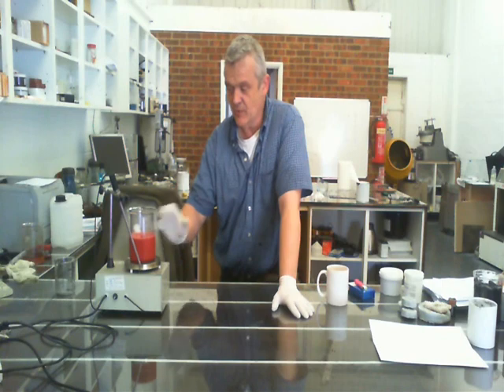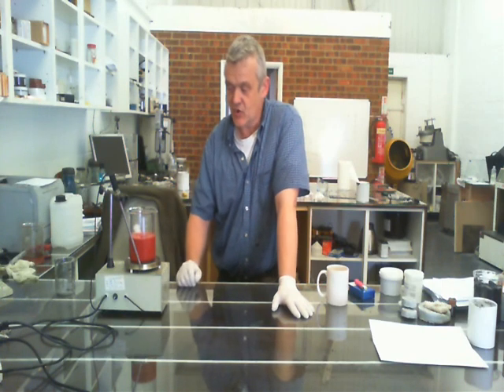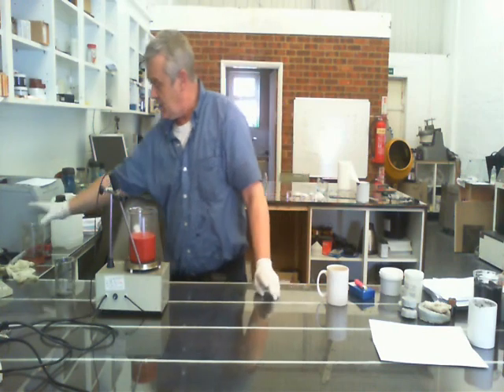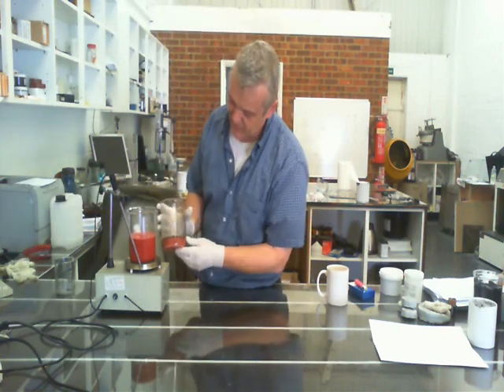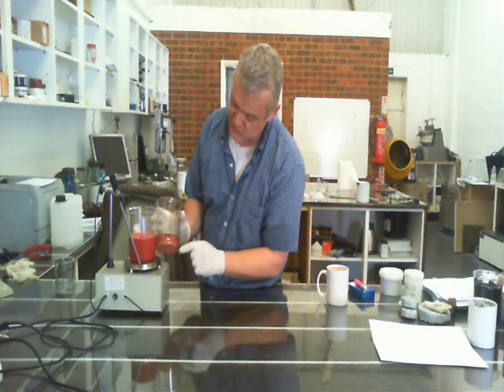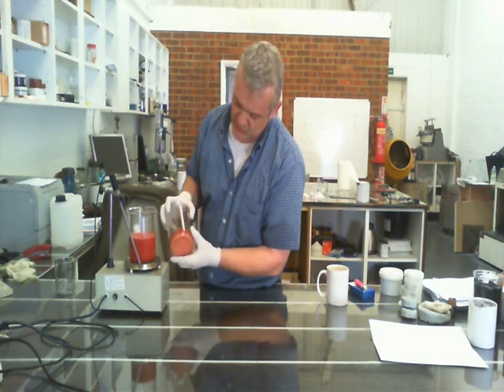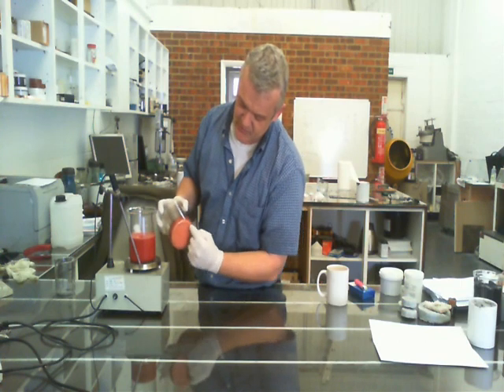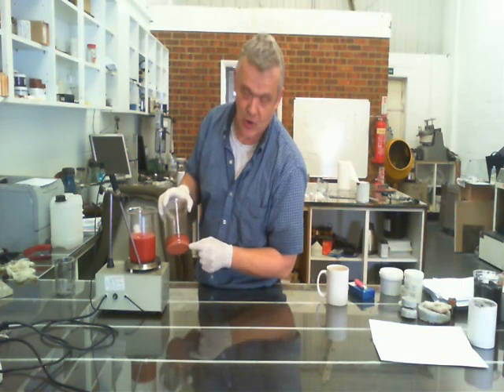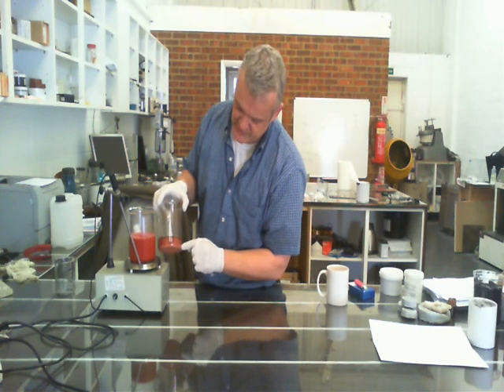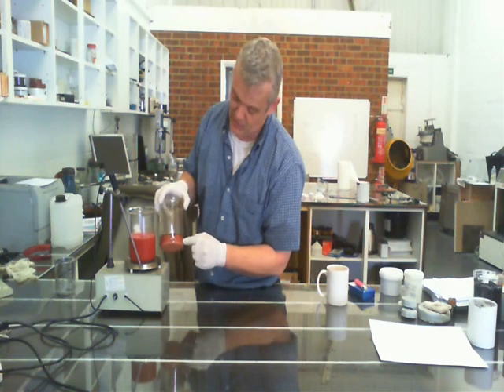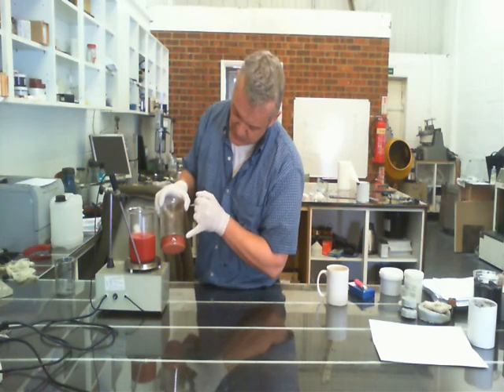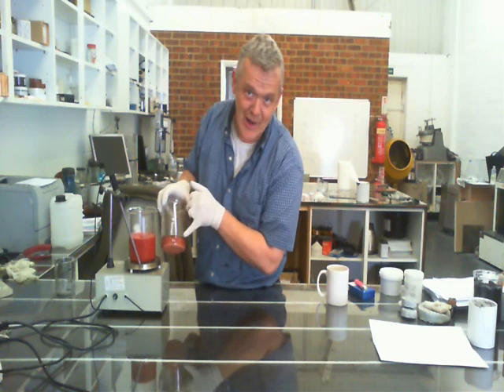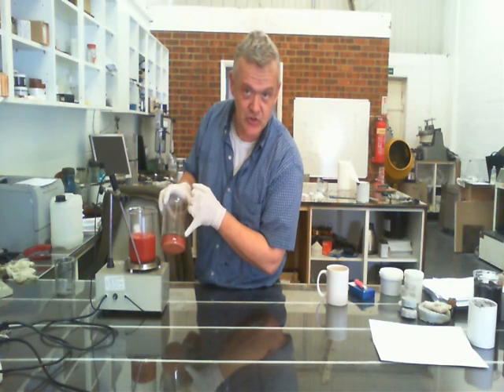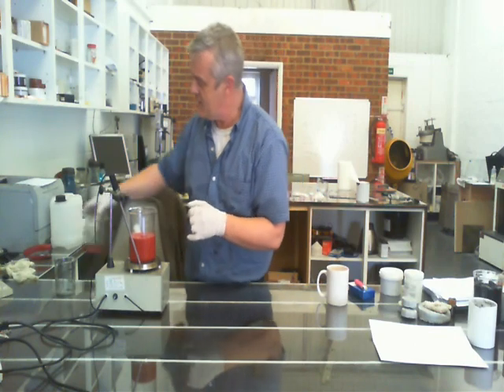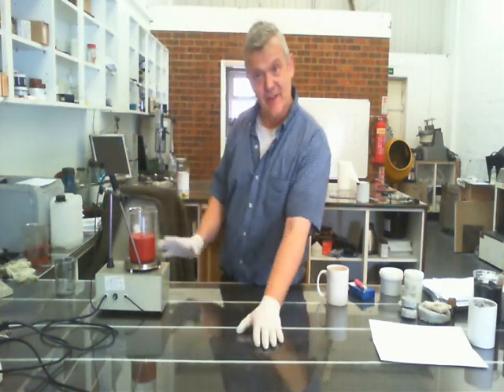Now over the next few hours, that will change colour. It'll go through from this brick red colour to orange to yellow to a kind of brownish colour. And here's one I actually did earlier so you get a colour comparison. So you can see how brick red that is and how brownish pink that is. Now when I made that first of all, I've got this very pink at the bottom here. They're quite large copper particles coated in gelatin. Then it goes to this brownish colour here. They're much lighter copper particles, again coated in gelatin. And then right at the top, I've got this kind of blackish brown layer, and those are copper nanoparticles coated in gelatin.